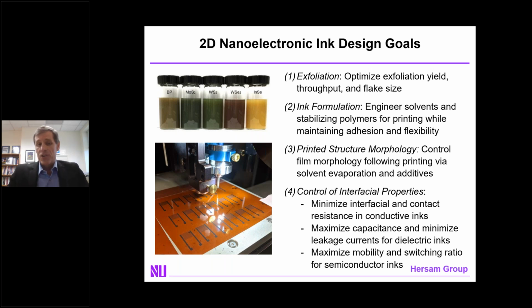The resulting structures are going to be much larger than the constituent nanomaterials, and as a result, they're going to be percolating networks. Consequently, the control of the film morphology will have significant control over the final properties, and this can be done via solvent evaporation and additional additives to engineer the final morphology. And then finally, we have to worry about interfacial properties, again, because these are percolating networks. For example, we want to minimize interfacial and contact resistance in conductive inks, maximize capacitance and minimize leakage currents for dielectric inks, and maximize mobility and switching ratio for semiconductor inks.